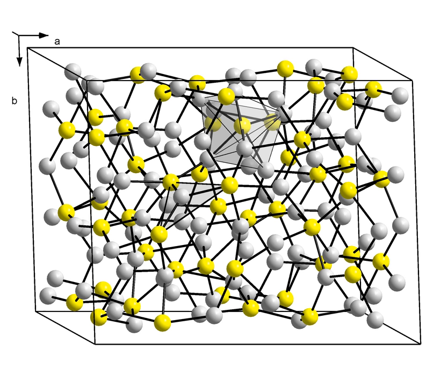In this structure there are 24 crystallographically distinct Cu atoms, and the structure has been described as approximating to a hexagonal close-packed array of sulfur atoms with Cu atoms in planar 3 coordination. This structure was initially assigned an orthorhombic cell due to the twinning of the sample crystal.